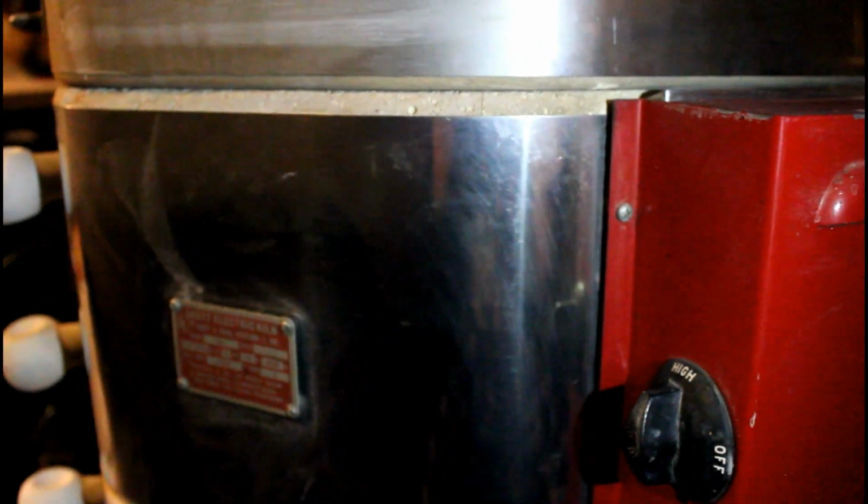2 hours later. So what you should do now is take out the little thing that was aerating your kiln, go ahead and close your kiln, plug up both of the peepholes, and go ahead and put both of your notches on high. The bottom one's on high, and the top one is on high. The kiln is closed, both of the peepholes are closed, it has enough oxygen in it, everything's warmed up to the proper temperature, and we're gonna check on this in the morning and see how it goes.